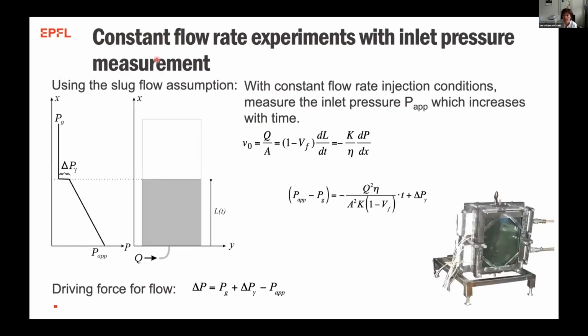With a constant flow rate experiment, solving the same equations that I showed before is very simple because Q is a constant. You impose a flow rate. So dL over dt is a constant. So the flow front moves linearly with time. And then what changes, of course, because this is constant, is that as L increases, P increases. So you have a pressure at the entrance that will increase linearly with time.